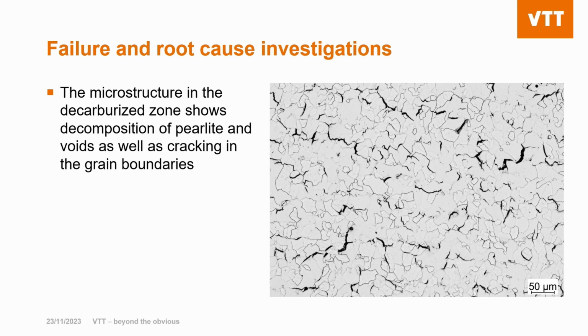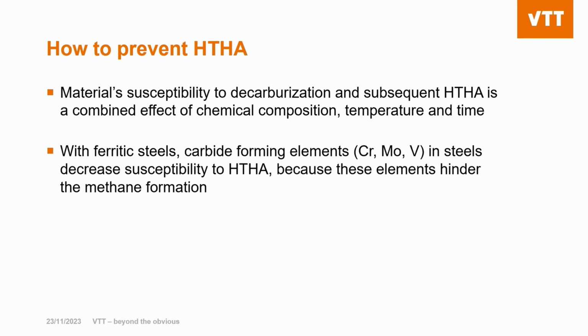So based on these investigations made at VTT and also based on the background data from the customer, it was evident that severe high-temperature hydrogen attack had occurred in this carbon steel pipe, which was in an older plant that had been converted into hydrogen service. Now, how to prevent this high-temperature hydrogen attack from happening?